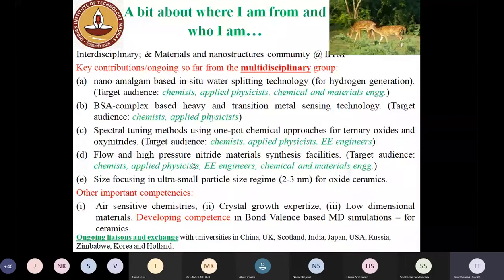Next is size focusing of ultra small particles. This is again something very, very cute. I mean, we ran into this entirely by accident, and I find it very fascinating. Typically, what happens is, and chemists here would know this, if you have a bunch of different sized particles, small particles and large particles, and you heat them up, then the larger particles would basically grow at the expense of smaller particles. By that, what I mean is small particles would get smaller and smaller, and the large particles would become bigger and bigger. And the argument for that comes from thermodynamics.